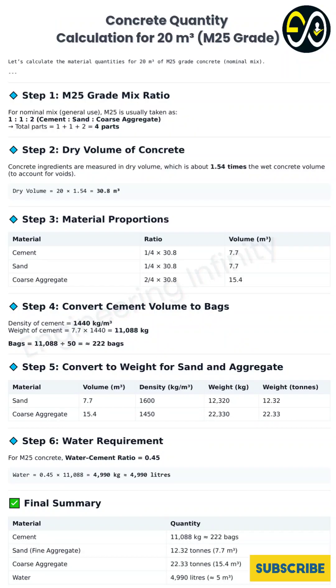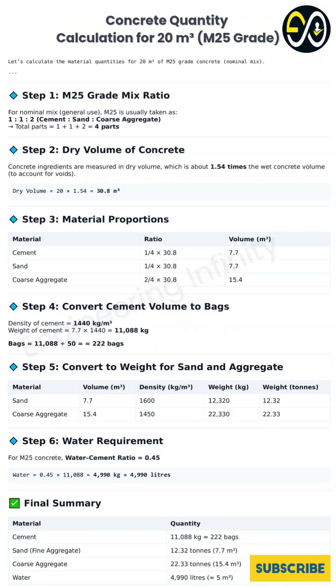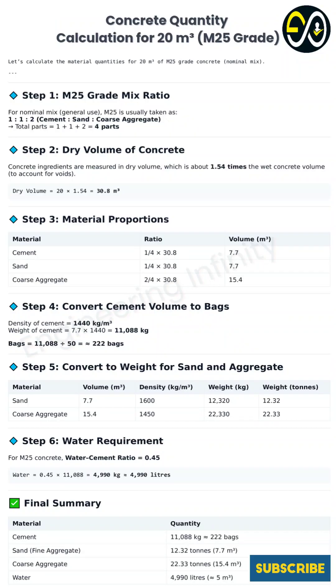Volume sorted. But suppliers don't usually work in cubic meters for everything, especially cement. We need weights — tons, kilograms. Different materials have different densities, so that 7.7 cubic meters of cement weighs very differently than 7.7 cubic meters of sand. For cement, the standard bulk density is around 1,440 kilograms per cubic meter. Sand is actually heavier, typically around 1,600 kilograms per cubic meter. And coarse aggregate — gravel and crushed stone — is usually around 1,450 kilograms per cubic meter.